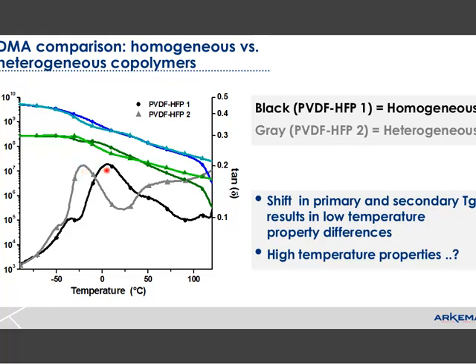We combined it in such a way that you can see that the tan delta has shifted. Now, in this particular region, down around -40, -50, that is the traditional glass transition temperature reported for PVDF resins. So we see a subtle shift in that Tg. So we know that this gray heterogeneous product is going to perform better at low temperature. Of more importance, though, is this secondary transition, which often is not reported. This transition is what controls low temperature impact. And in this case, by making this heterogeneous product, we can get down to about a -30 degrees C impact.